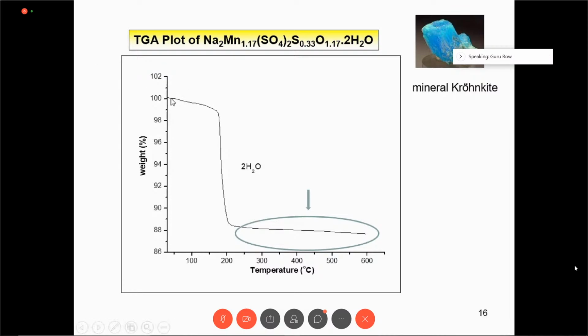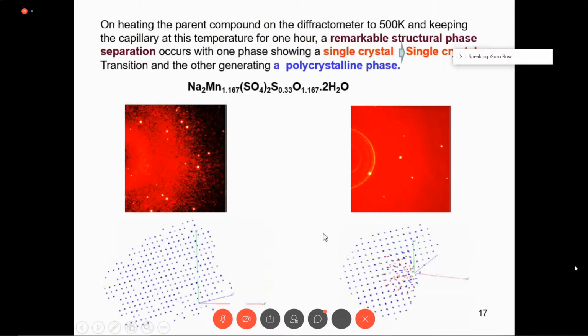And as we go along, we check the nature of the material. Since we have this evidence from the thermogravimetry that at around 180 degrees, there is a change of phase, that means there is a phase which is going from this compound to some other compound. What is that other compound which we get? When we look at that on the machine, for the first time we saw a remarkable structural phase separation. The phase separation occurred with one phase showing a single crystal to single crystal transition. These spots which are seen here show the nature of the single crystal. And the spots we see here are the nature of the single crystal which formed after the phase transition.